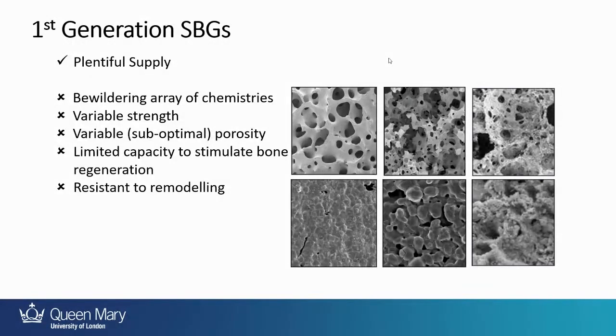So the macrostructures were variable. Again, from one material to the next, you've got a different porosity. And then also the microstructures were variable. So you can imagine, using a scanning electron microscope at much higher magnification, looking at what the structure is of those little struts that you can see in the bits of bone graft. Some of them had porosity in them and some of them didn't. And this range in strengths, range in structures, range in microstructures meant that the materials that are out there have variable strength, variable and suboptimal porosity.